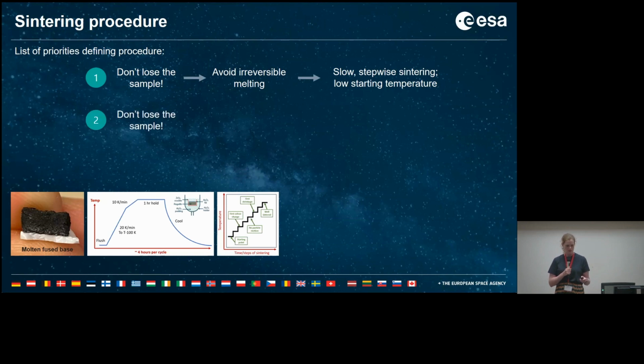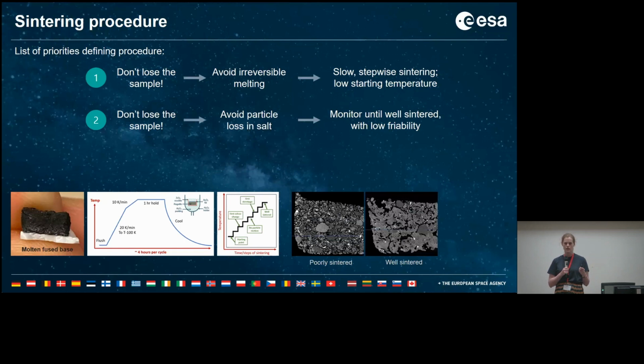The second priority was, again, don't lose the sample. But in this case, we wanted to avoid losing it in the salt during the processing. So we didn't want the pellets to be friable and have particles coming off them. So we monitor the process using XCT until it's very well sintered. And finally, we do want to aim for the best possible properties for FFC processing. So that means we need to maximize the open porosity because we need salt flow through the materials.